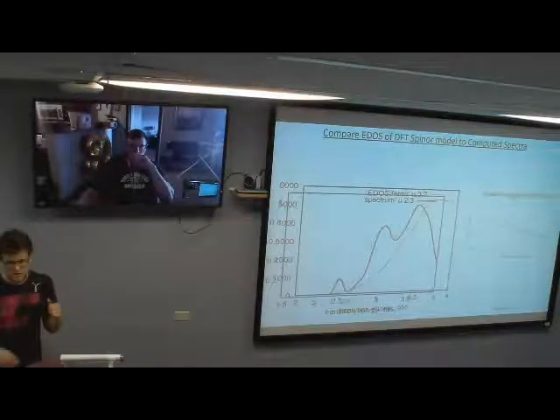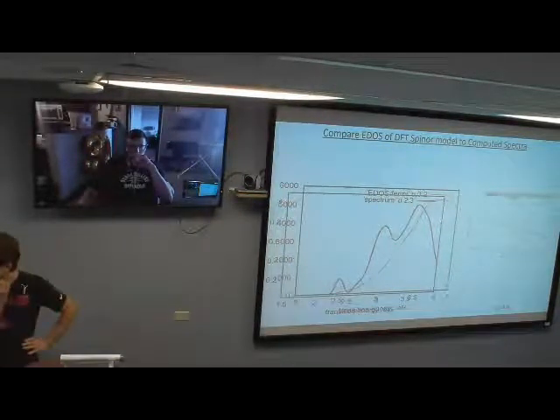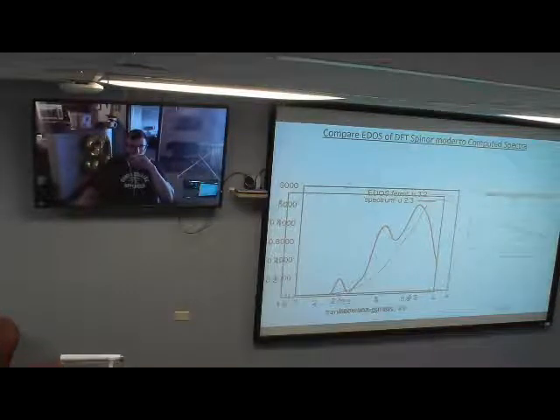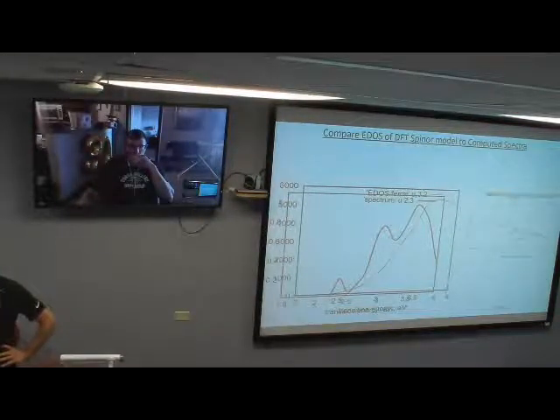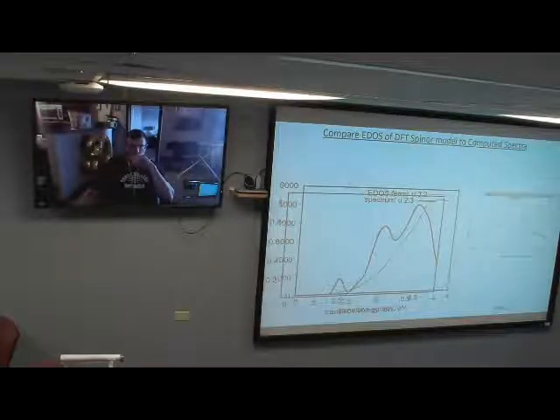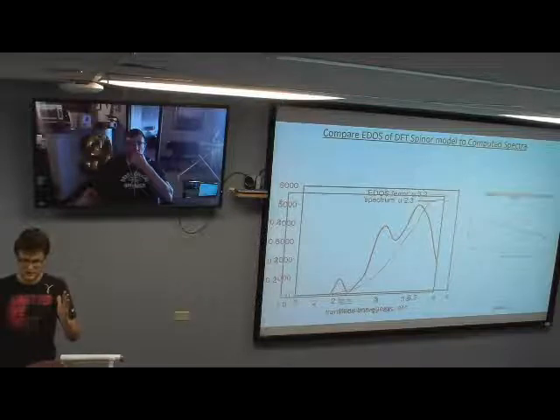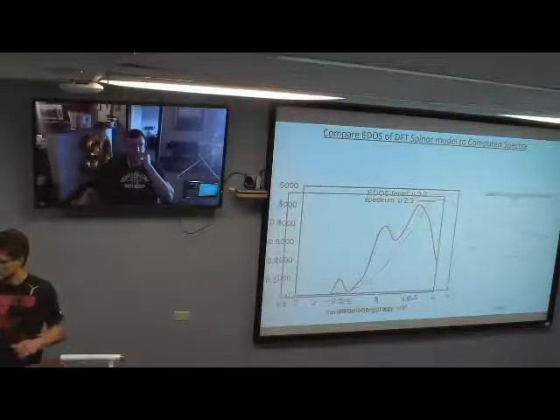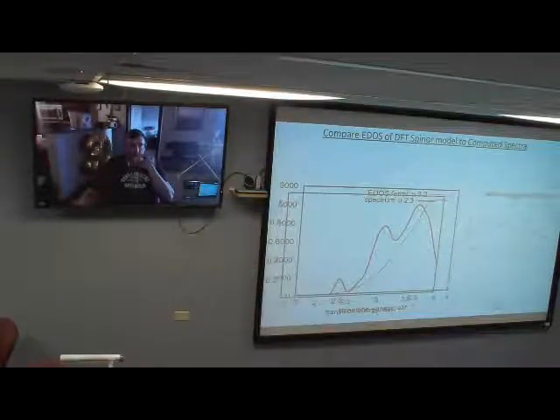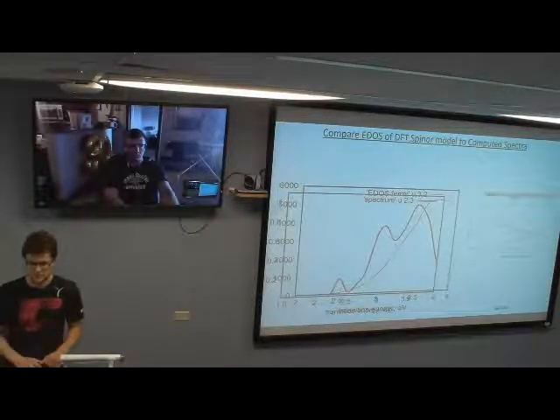So your x-axis is the energy of excitation, right? Y is oscillator strength on a log scale, and x is your energy difference, the energy of the exciton, right? Yes. Okay. And so that's how this purple figure turns into this red one. The higher in energy you go, your transition probability becomes exponentially less. But you have a lot more transitions, so your peaks are more resolved with each other than compared with EDOS.